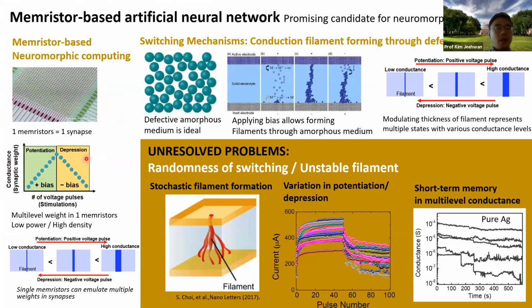In one memristor, you can register multiple values of conductance. By applying a voltage pulse to the memristor, you can update the conductance level inside the memristor, which is equivalent to the synaptic weight. If you apply a positive bias pulse, you can continuously register different levels of conductance value. If you keep applying the positive bias, you can enhance the conductance value. On the other hand, if you apply a negative bias, then you can reduce the conductance level.